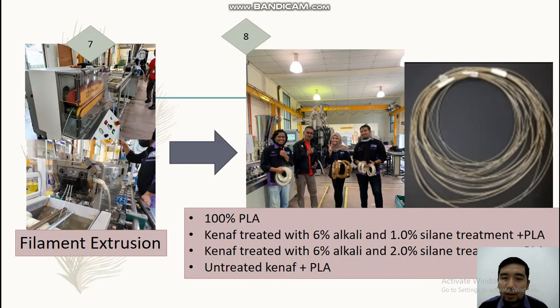Okay, after the test of the fiber, we use filament extrusion for 4 samples: 100% PLA, Kenaf treated with 6% alkali and 1% silane treatment with PLA, Kenaf treated with 6% alkali and 2% silane treatment with PLA, and untreated Kenaf with PLA. We can see in figure 8 the filament of our project. This filament extrusion was made at UniKL MIMET at Alor Gajah.